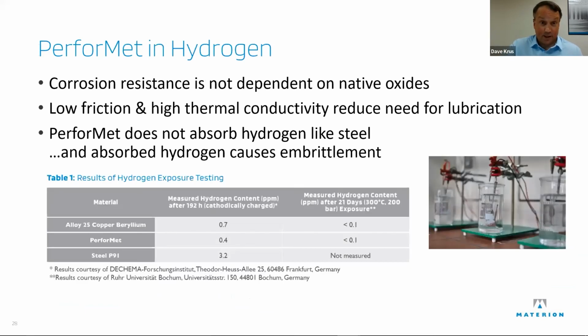And we took a look, went to a couple of very August universities in Germany and did tests like you see over there on the right, and found out that, we know from our oil and gas experience that copper beryllium doesn't absorb a lot of hydrogen, doesn't have hydrogen embrittlement issues. PerforMet absorbs a fraction of that even. And like whatever that is, an eighth of what steel absorbs. And then without the cathodic charging, without forcing the hydrogen into the sample, just nothing gets in.